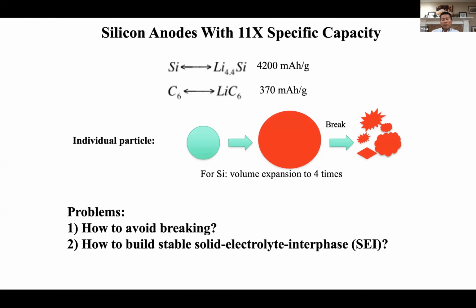So let me start from silicon. This new material is very exciting right now. Of course, it's full of problems. Silicon has this big volume expansion of 4 times, causing the material to break, and also instability of the solid electrolyte interface. Once you have expansion and contraction going on during charging and discharging, there's no way you can form a stable interface.